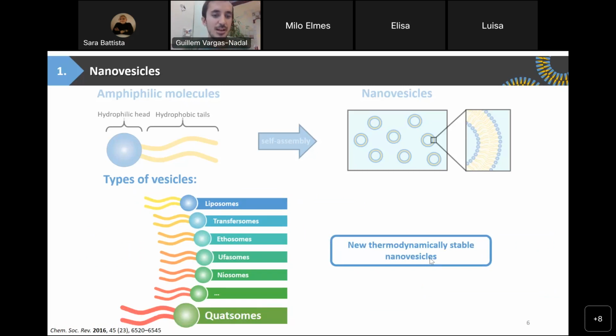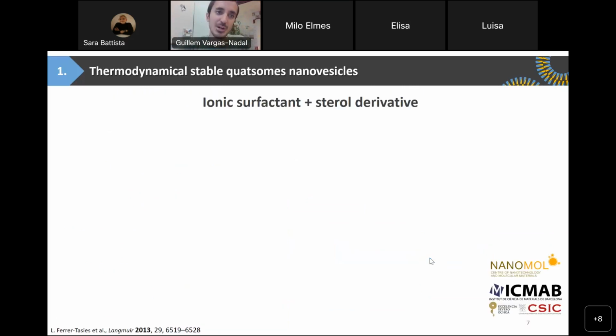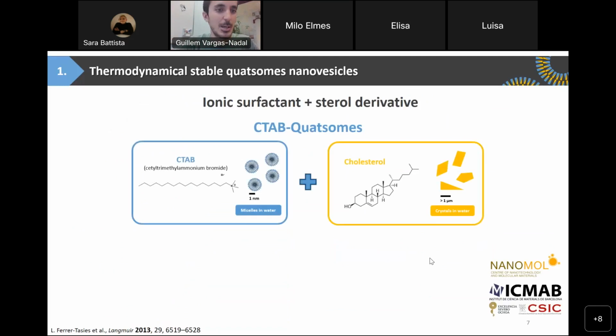And here, for example, are quatsomes, which are thermodynamically stable nanovesicles. But what are quatsomes? Quatsomes are composed of an ionic surfactant and a sterol derivative. So for example, the CTAB quatsomes, which are the most studied quatsomes, are composed of CTAB as a surfactant and cholesterol as a sterol derivative. In this case, the two molecules in water behave completely differently. As you can see, the CTAB in water forms micelles. However, the cholesterol in water forms crystals.